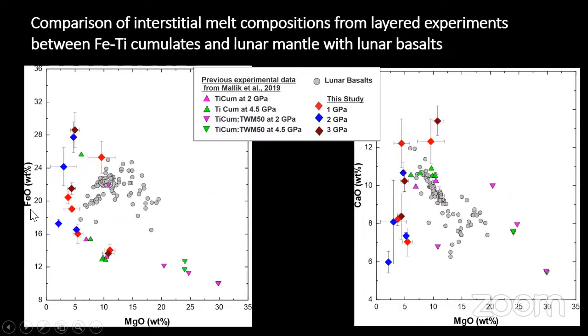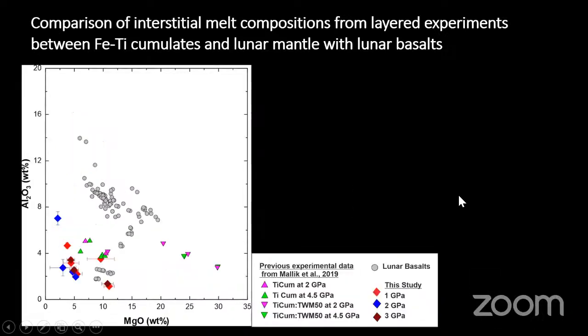The FeO-MgO plot shows that the FeO content of our interstitial melts is at par with the lunar basalts, but overall, in all the diagrams, we can see that our melts are low in MgO compared to the lunar basalts. CaO is also at par with the lunar basalts, but for Al2O3, the aluminum oxide, our melts are much lower in aluminum content. The lunar basalts have much higher aluminum content.